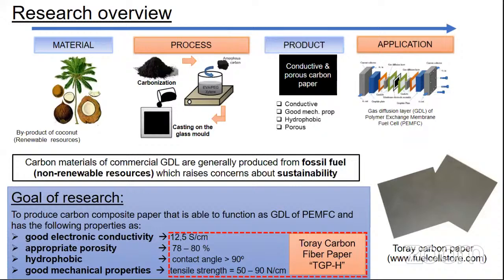The goal of our research is to produce carbon composite paper that is able to function as GDL of PEMFC and has the following properties. This one. In addition, we use commercial carbon paper that is established in use as GDL in PEMFC, such as Toray carbon paper, for comparing the properties of our sample. If the properties of our sample are similar or close to the Toray carbon paper's properties, it indicates that our sample is ready to be applied as GDL in the PEMFC system. We have to make sure of these values first before the application process in the stack of PEMFC.